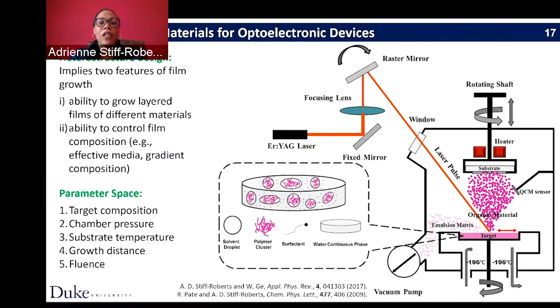And so because of this, you can start to do heterostructure design in organic and hybrid materials using polymers that's not really possible in a lot of other techniques. And so when we think about the parameter space available to control this, the most important parameter is the target composition, the chemistry that's used to create this emulsion, but also the chamber pressure, the substrate temperature, the distance from the target to the substrate, and also the fluence or the power of the laser that's coming in.